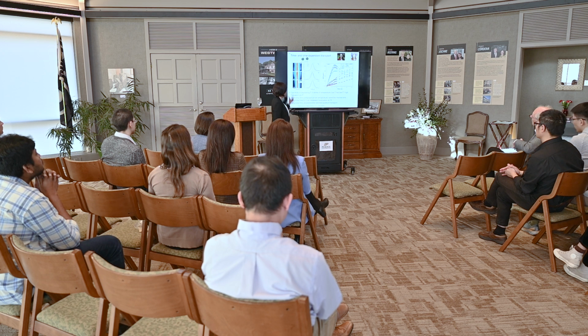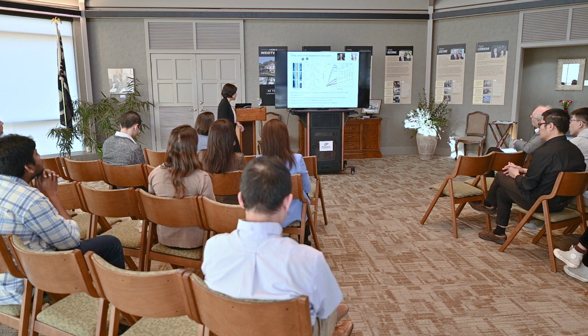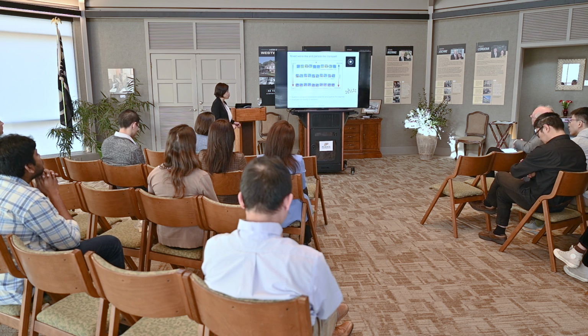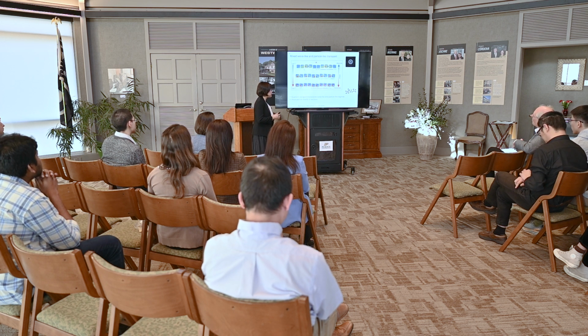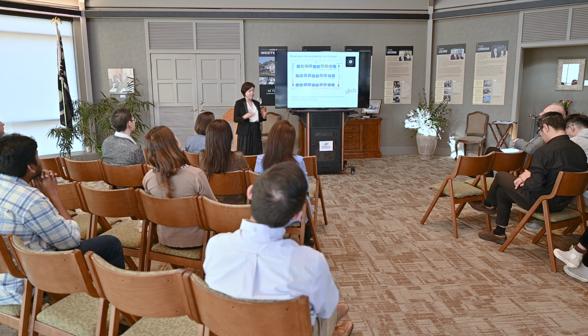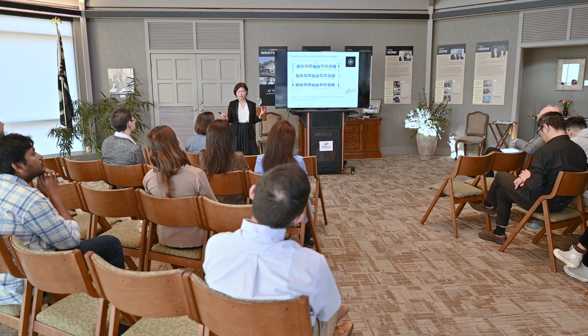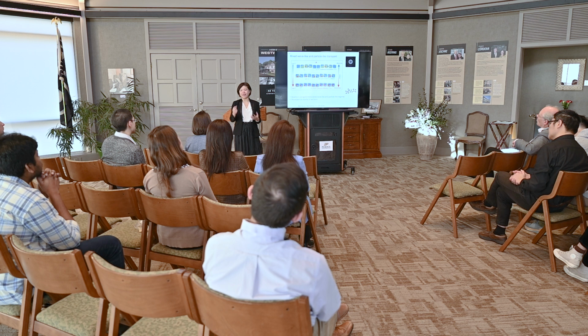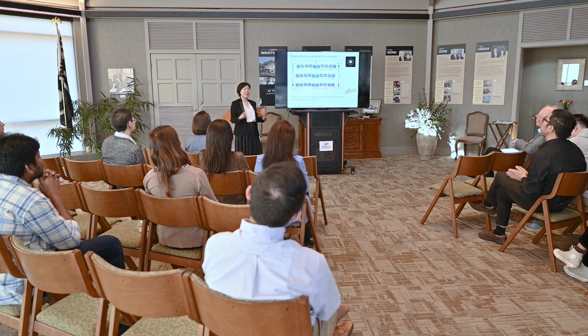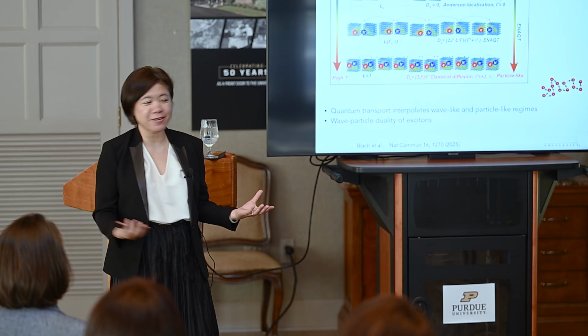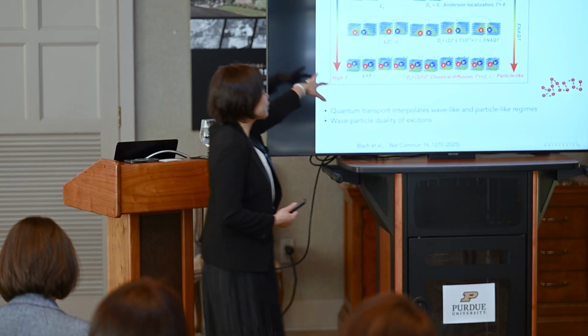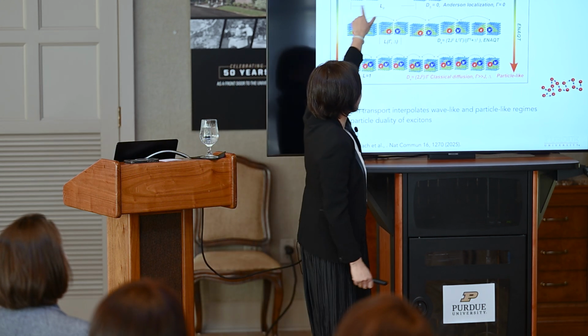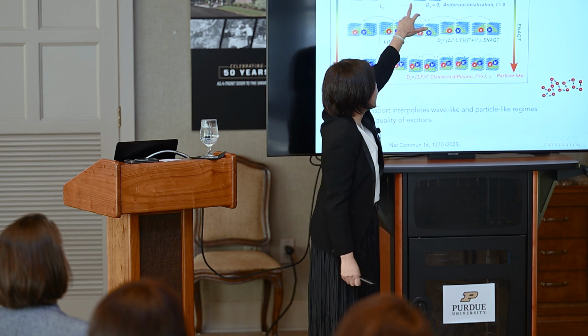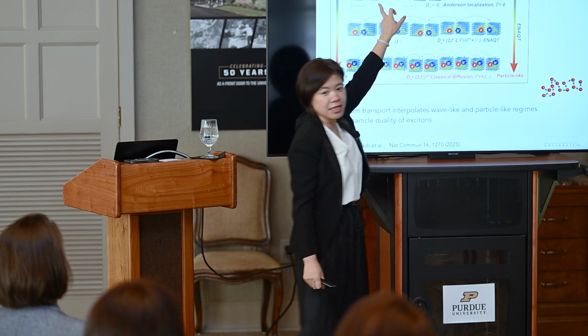This is actually a very interesting thing, because what we really want to understand is: does this exciton, which is a quantum particle with wave and particle-like behavior, move as a wave or as a particle? And the answer is they move as both, because they are both wave and particle. What is really cool is that at low temperature, the exciton first propagates very, very fast because the exciton waves can be over many, many quantum dots.